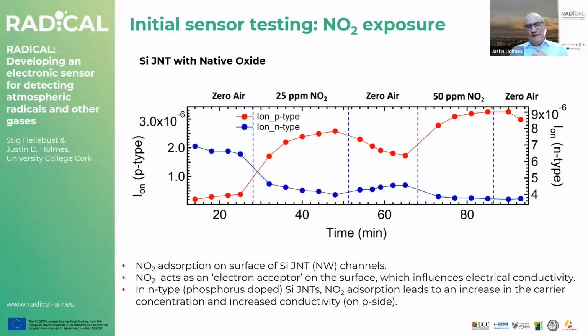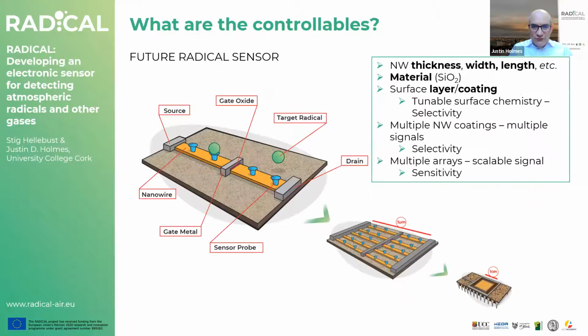This NO2 adsorption leads to an increase in the carrier concentration. When we're looking at P, that's the red line, it leads to an increase in conductivity on the P side and a decrease in conductivity on the N side. So what we need to do then is ask, is this data meaningful? Are we seeing any real effect of the NO2 on the device? And I think that's where I hand over to you, Stig. So I'll stop sharing.